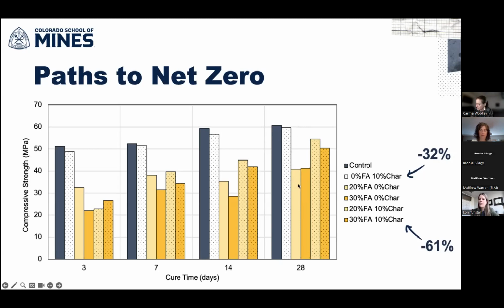And then when we include fly ash and no biochar, we see a pretty significant strength reduction at 28 days. And this is typical for fly ash. Fly ash, you get benefits at later ages. 28-day strength is often lower with fly ash mixes. However, if you include both fly ash and biochar, you get increased 28-day strength compared to just the fly ash alone. And we would anticipate that you would get further strength improvements at, say, 56 days, which is typical for fly ash mixes. So this is just demonstrating feasibility. This mix here on the bottom, the 30% fly ash, 10% char, that would be associated with a 61% offset in carbon footprint. So, just pushing the boundaries here and trying to get better and better for carbon neutrality in these mixes.